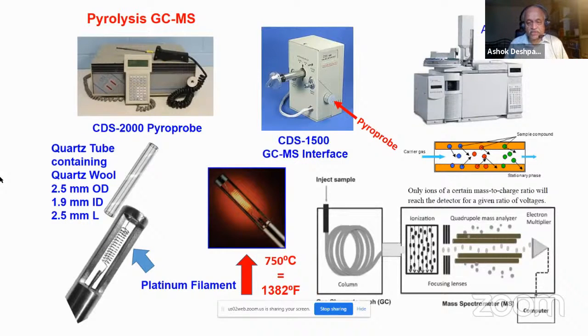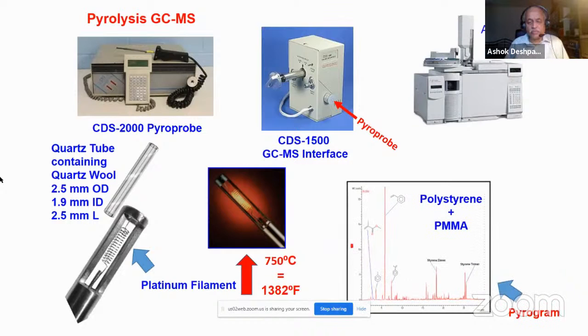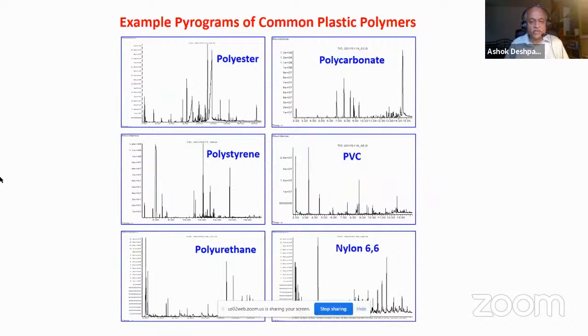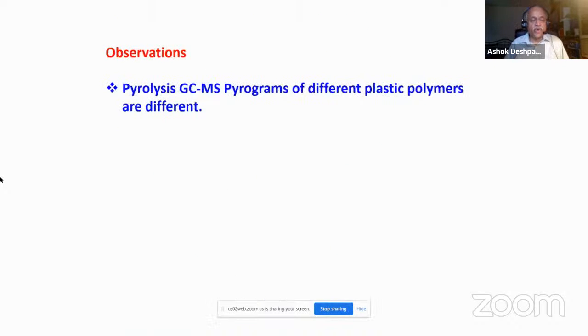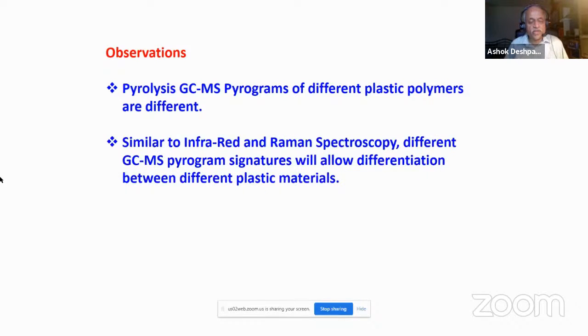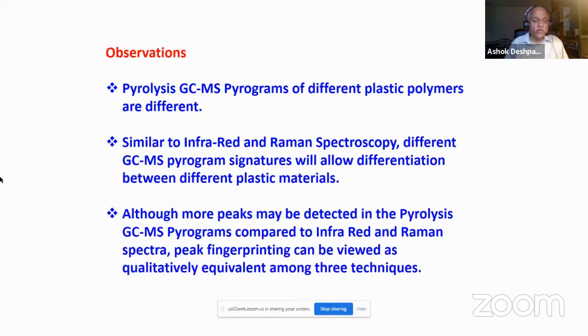The sample is separated on a gas chromatographic column and analyzed by mass spectrometer to give a pyrogram which is indicative of the polymer. So these are the examples of various commonly used plastic polymers. The observations are that the pyrolysis GCMS pyrograms are different for different polymers. Similar to infrared and Raman spectroscopy, different pyrograms will allow differentiation between different plastic materials. Although more peaks may be detected in the pyrolysis GCMS pyrograms compared to infrared and Raman spectroscopy, the peak fingerprinting can be viewed as qualitatively equivalent among the three techniques.